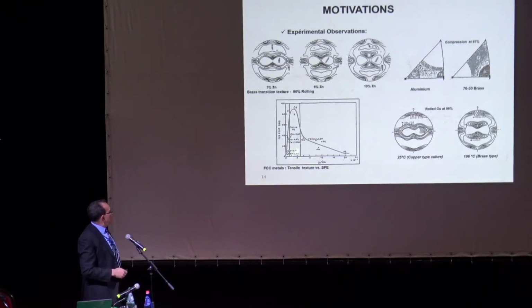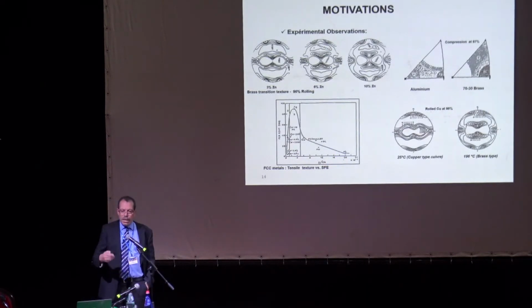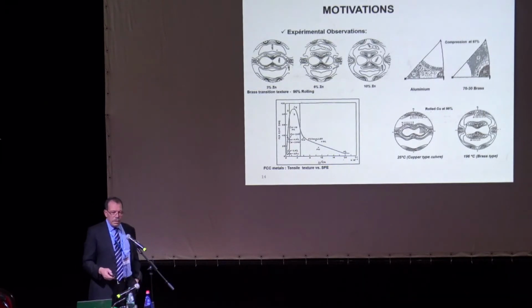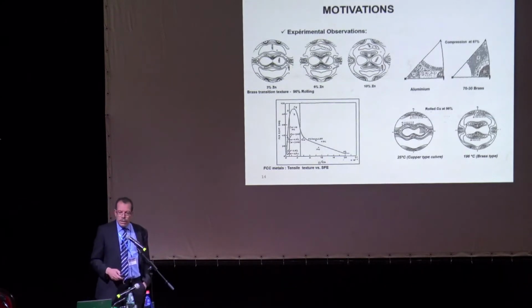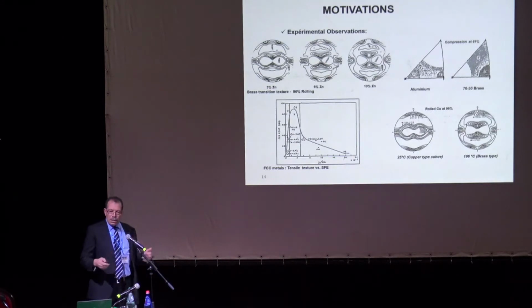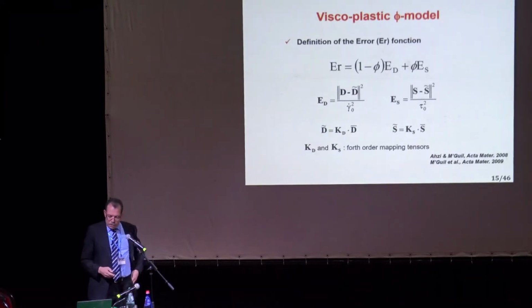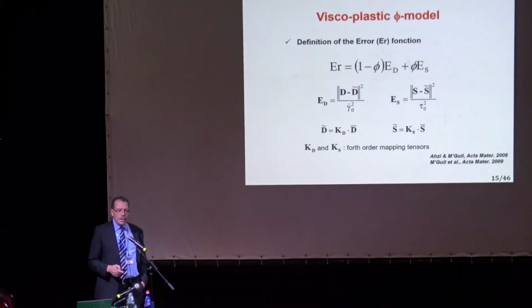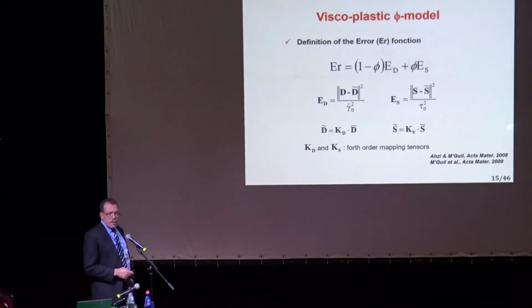There is some old work that has been done to show the effect of stacking fault energy. So stacking fault energy may have something to do with it, which in fact may affect the slip activity and the cross slip and so on within the single crystal. And there might be other reasons that I will mention later on. So that's why we decided to look for a different way of developing an interaction law, okay, that links the local field to the macroscopic fields. And what we did here, instead of using integral equations or so, we just looked at the error.